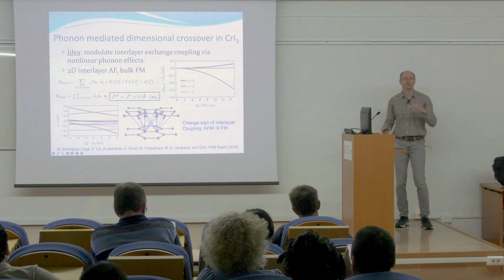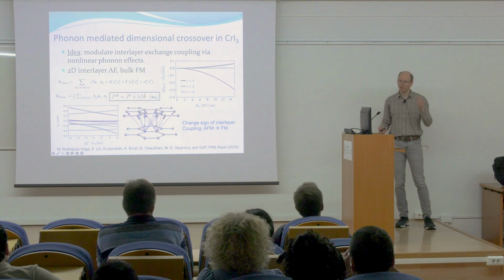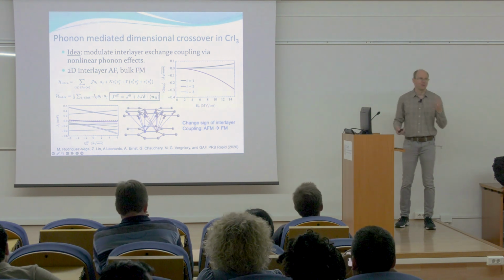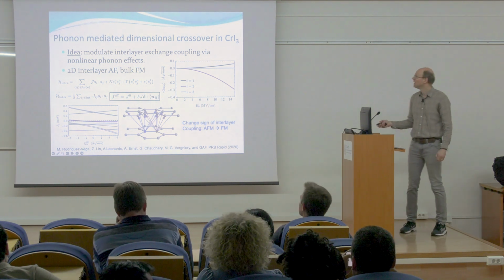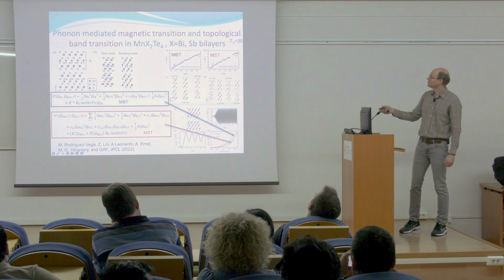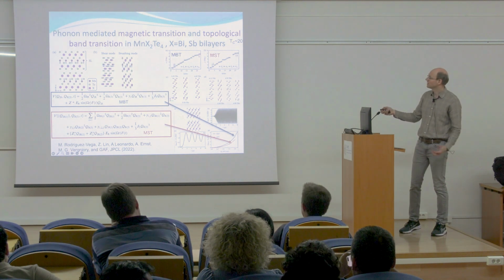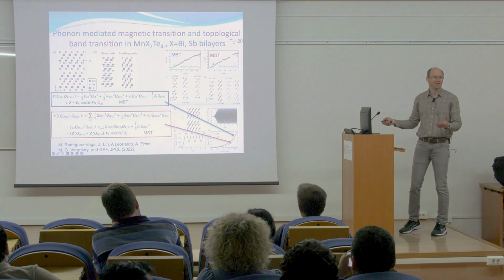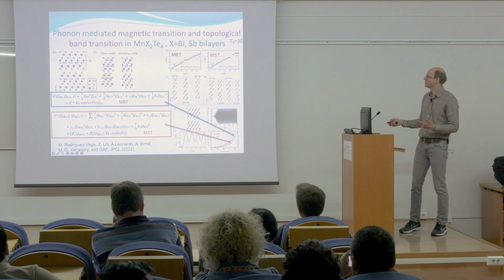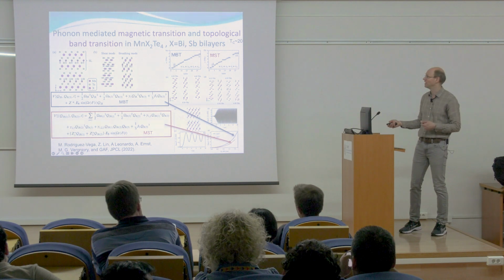And this is a reversible process. It can be done more or less instantaneously. And so it gives great control over the material. And then we looked at another material which, in addition to a magnetic transition, also has a topological band transition. And we found that that topological band transition goes hand in hand with the magnetic transition.